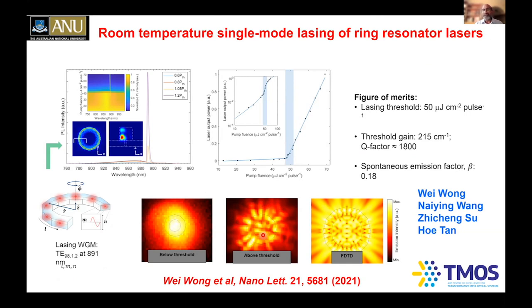And again, you can see the comparison of the theoretical simulations, the FDTD simulations, finite difference time domain simulations, and experimentally measured patterns, and they really match very well. And again, this threshold-like behavior, S-type behavior, very narrow line width, indicating that, again, Wei Wong's hard work really paid off. And then he is able to show that these ring resonator lasers are very good for photonic integrated circuit applications also. And other colleagues are also involved in this particular work, whom I've listed here along with Wei Wong.